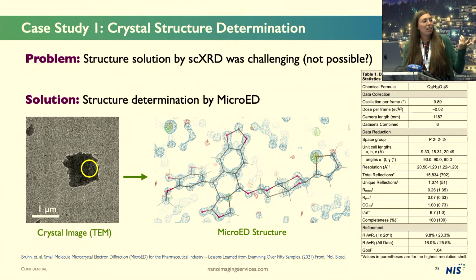This is what I would say is a more lower quality structure. The resolution of these crystals is about 1.2 angstroms. Despite that, we were still able to phase this data, get a pretty reasonable structure, and assign all of the non-hydrogen atoms pretty confidently. So we were pretty happy with this. It's deposited. You're welcome to check it out.